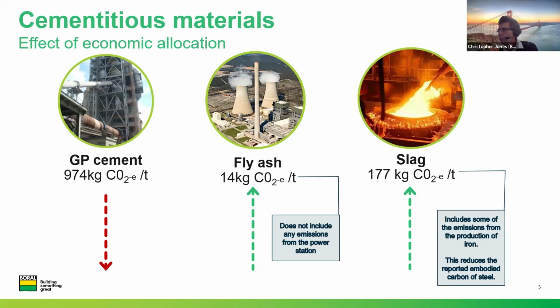Economic allocation is a way of determining the embodied carbon of co-products. Co-products are two or more products that are produced from the same process. We don't want to allocate all the emissions to both products, so we allocate the emissions based on the value of each product. Fly ash is considered a waste product with no value to the producer. Power stations do sell the ash to cement suppliers, but the money they make is so low that it is deemed negligible. So the embodied carbon of fly ash at the power station is zero, and only the emissions from the transport to the plant are attributed to the fly ash.